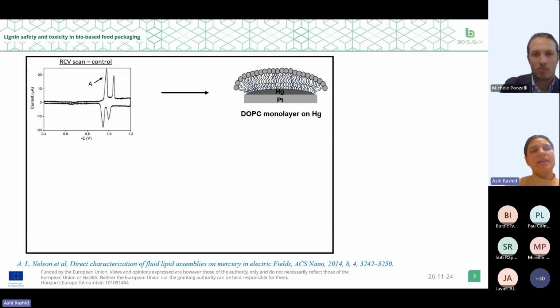So here is the RCV scan, which is a very characteristic frame of a very good, compact and impervious lipid layer on the surface of the electrode. It has different distinct regions which correspond to different phase transitions, for example, the constant current region and the two sharp current peaks.